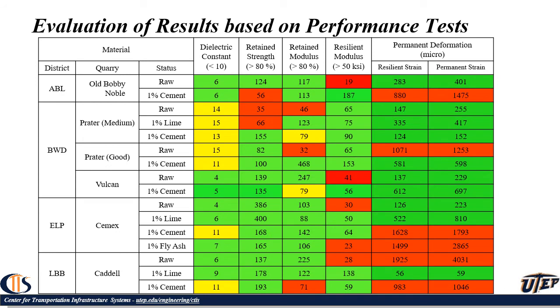Then we started looking at the performance of these materials now that they were considered grade 1, and we started looking at the values that I discussed to show the performance. And you see that even though we were passing now with 1% cement, we are not fulfilling the permanent deformation. So we're going to get a settlement in the base material if you use it even with 1% cement. So we have to be careful.